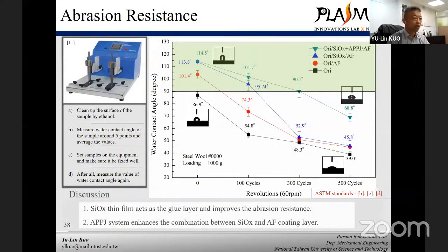However, if you try to use this kind of coating for industry, you have to do something more serious, such as testing the abrasion, because you have to let the industry know that the abrasion resistance is still quite high. The industry gave me the standard. They say that for the abrasion resistance test, the surface contact angle should be higher than 90. So you can see the original sample under abrasion testing, for cycles from almost 100 cycles to 500 cycles.